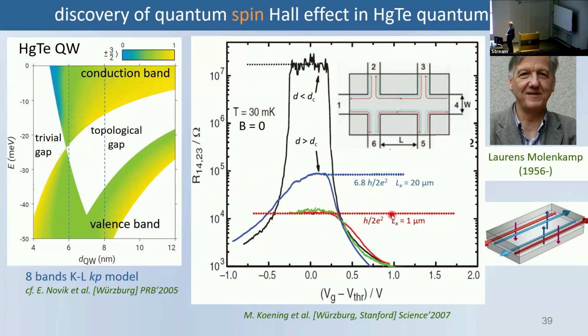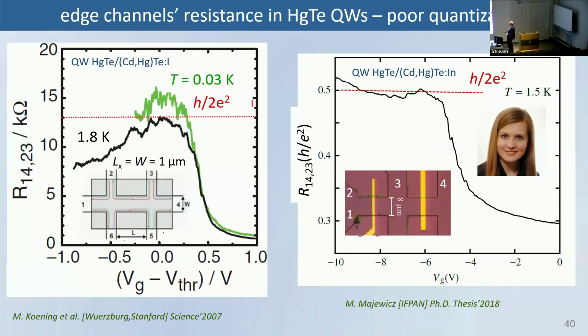Unfortunately, what you see here is that this quantization is very poor. You have to take a very small sample to have something which was predicted theoretically. If you take a longer sample, something is wrong, this quantization does not occur, or is far from it. And this is shown here, how it looks at two temperatures, so you cannot say that this plateau is as before, with accuracy 10 to minus 10. Here the accuracy is maybe a factor of 2 or something like that. And also if you take gates, finger gates, you end up with the same situation, that quantization is not very good actually. So now the question is, what is the reason?